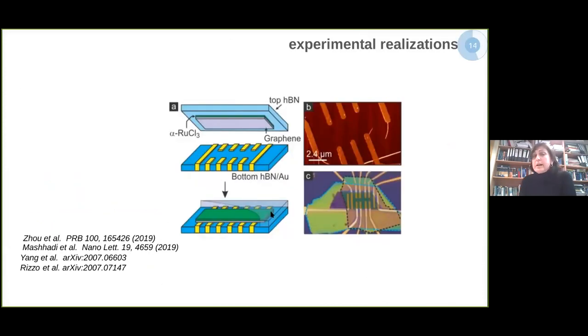And there are right now quite a few labs that are realizing devices of these heterostructures. Here I'm showing the device of the group in Stuttgart, Burkhard and Klaus Kern's group. They sandwich alpha-RuCl3 and graphene in layers of hexagonal boron nitride. And here are the gold electrodes in order to measure resistivity in this heterostructure.